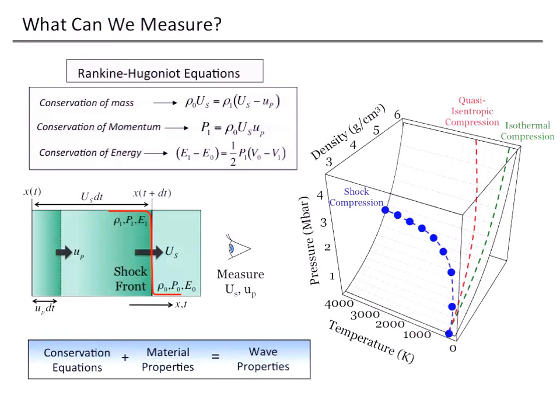Essentially a qualitative way of thinking about this is that we're measuring the wave properties. We know the conservation equations, and that allows us to solve for the material properties. These equations define a relationship between pressure and density, which is this blue curve schematically in this diagram. So when you do a given experiment, you land somewhere on this blue curve depending on how hard you drive your shock. But these equations don't tell us anything about the thermal state - they don't give us any temperature information. And actually, temperature turns out to be a really unique way of looking at the properties of these materials.